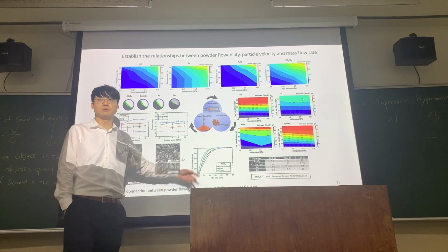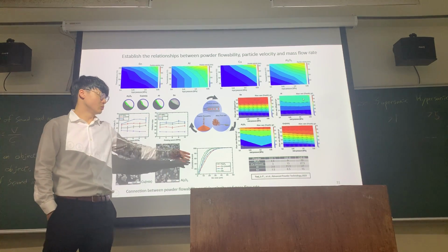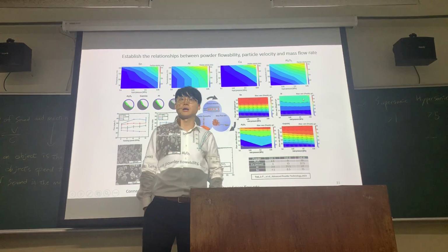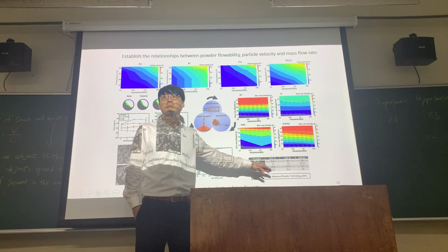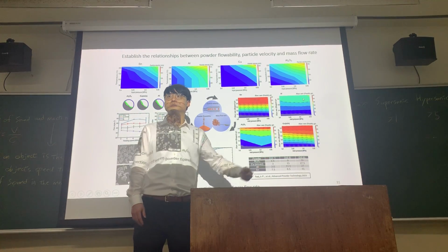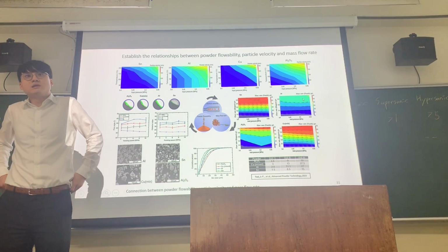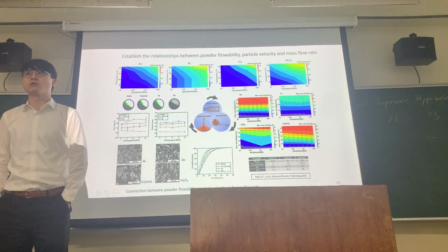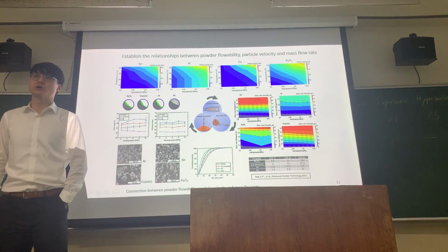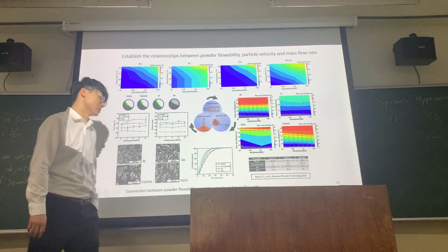And a very common terminology you can see is the particle size distribution, where we categorize as D0.1, D0.5, and D0.9. So 0.1 means it's at the 10% of your distribution, while 50% is the median and 90% is at the 90%. So when you read the particle size distribution from the particle size analyzer, sometimes it might be a little bit tricky reading this data because you're assuming this is a normal distribution, right? Normal distribution.